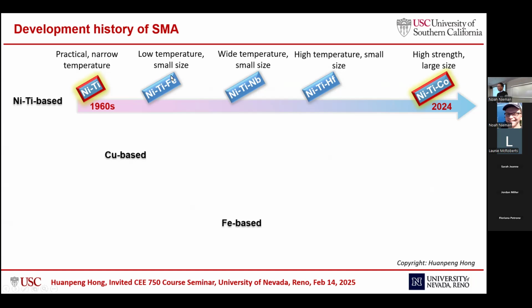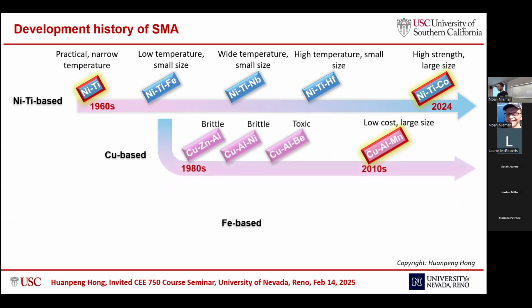And if we add iron to it, this alloy behaves better at low temperature, but it's only available in small size. And nickel titanium niobium has a wide temperature range, but it's also only available in small size. And nickel titanium hafnium works at high temperature, but it's only available in small size. The small size here refers to around 1 millimeter or less than 5 millimeter diameter wire or thin strips.